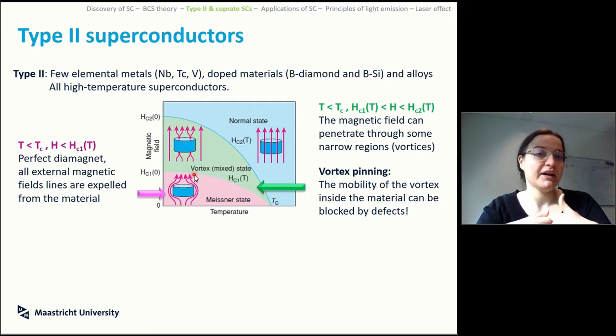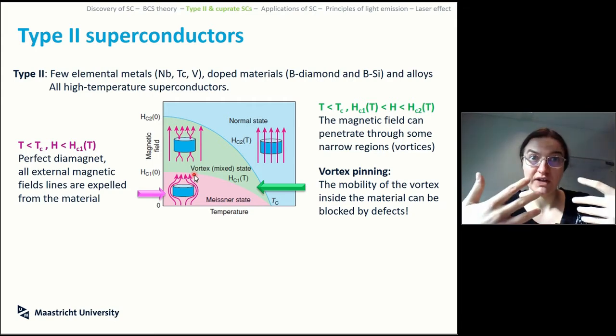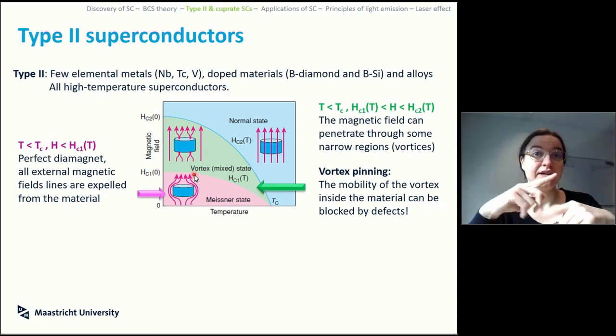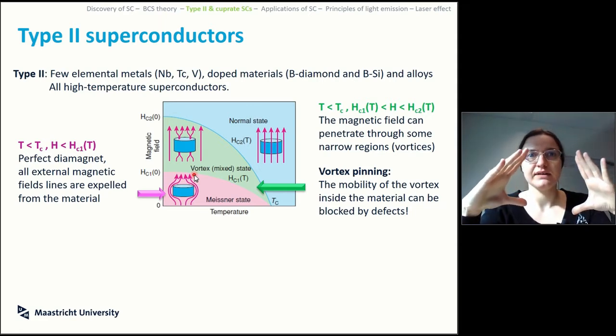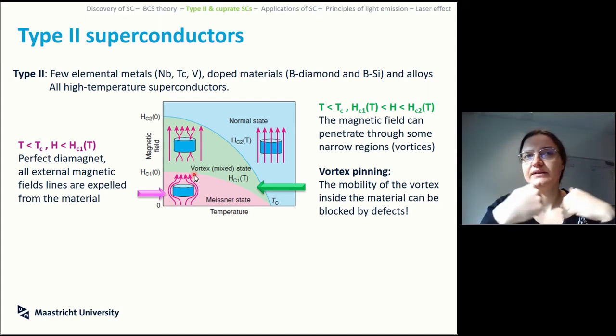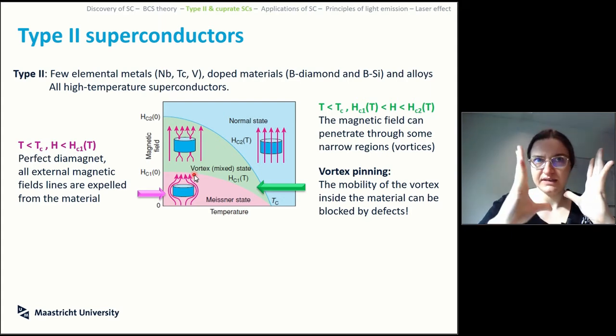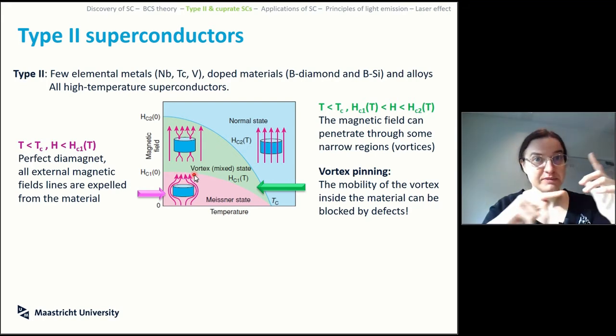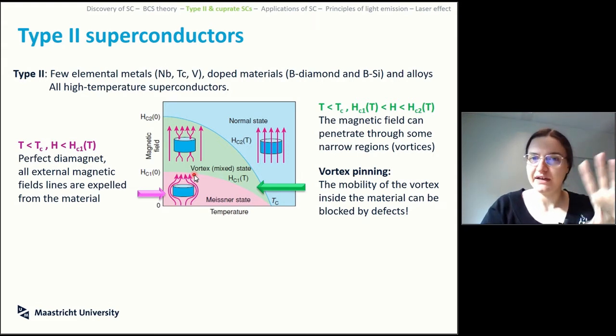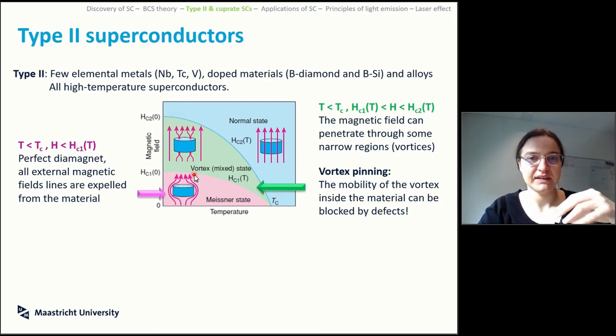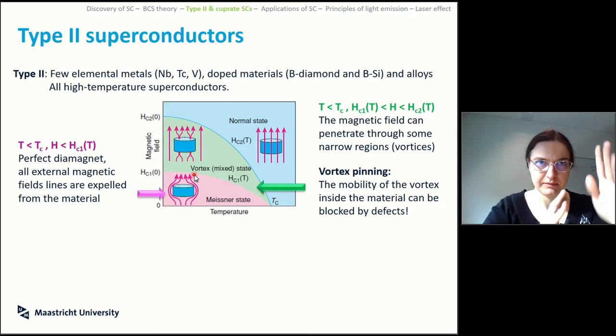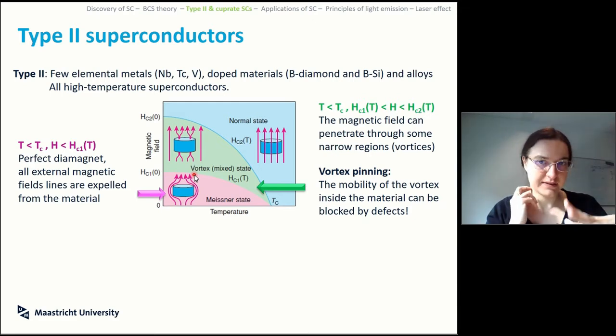When the vortices are unpinned, and you have several of them, they will spontaneously arrange themselves in a way that optimizes the repulsion, because a vortex doesn't like other vortices. So as a series of magnetic field lines passes through, you find yourself with multiple vortices, and these vortices will arrange themselves in a hexagonal shape or something like that. It's particularly mesmerizing to look at. And if the vortices are pinned, but still form in a very random way, then you can call it a vortex glass. So you see this passage of vortices, and it's still a very peculiar state.